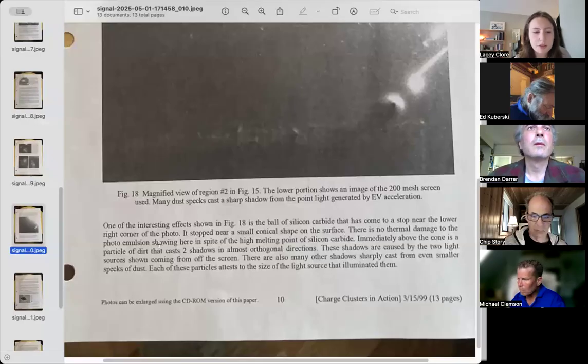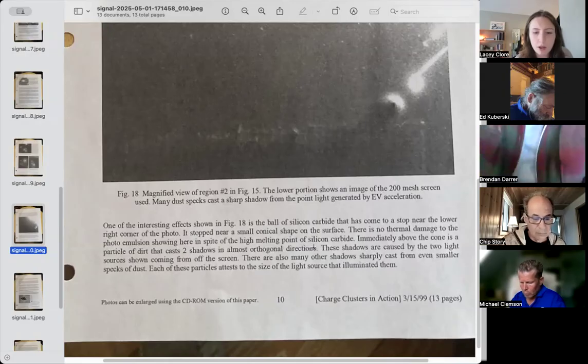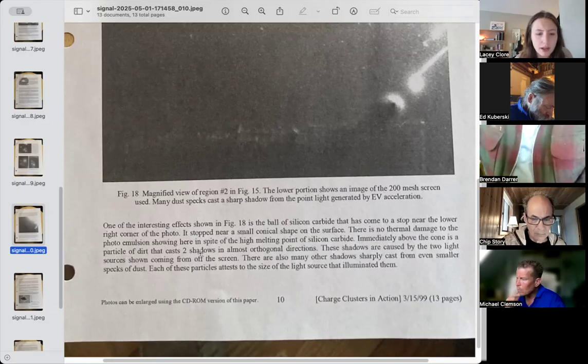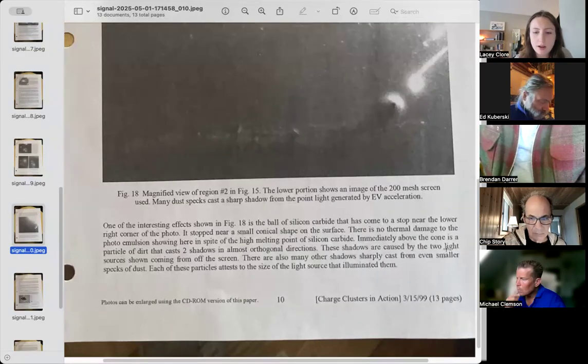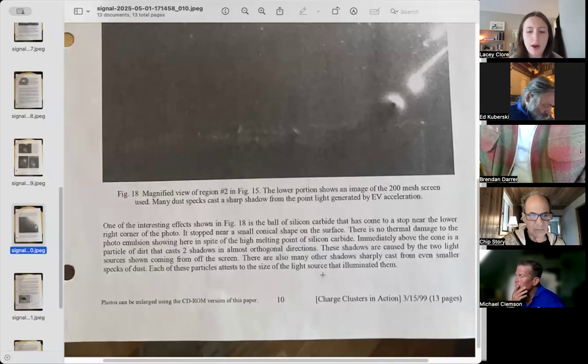There is no thermal damage to the photo emulsion showing here in spite of the high melting point of silicon carbide. Immediately above the cone is a particle of dirt that casts two shadows in almost orthogonal directions. These shadows are caused by the two light sources shown coming from off the screen. There are also many other shadows sharply cast from even smaller specks of dust. Each of these particles attests to the size of the light source that illuminated them.